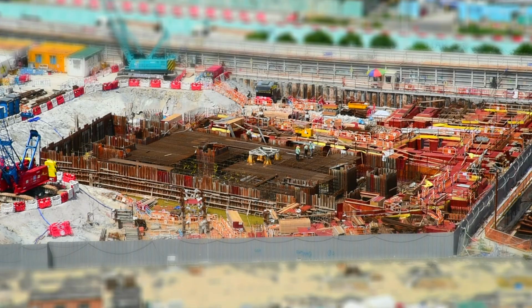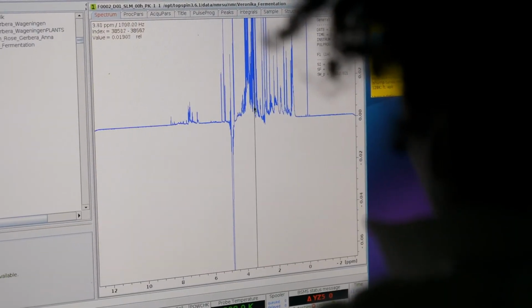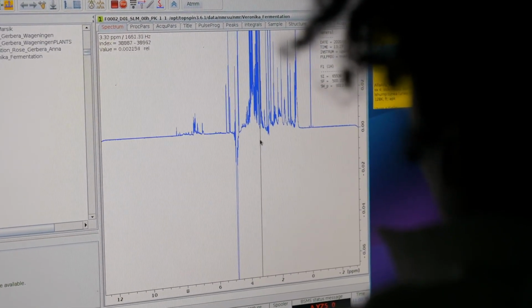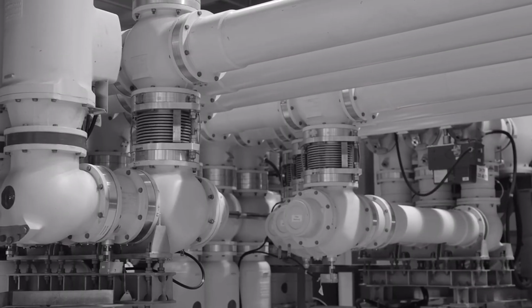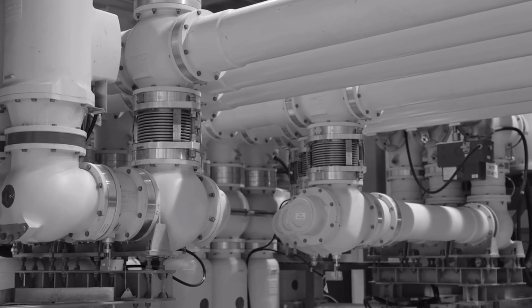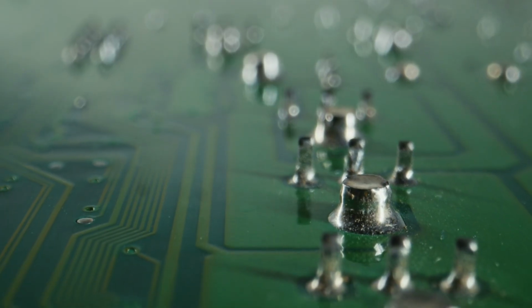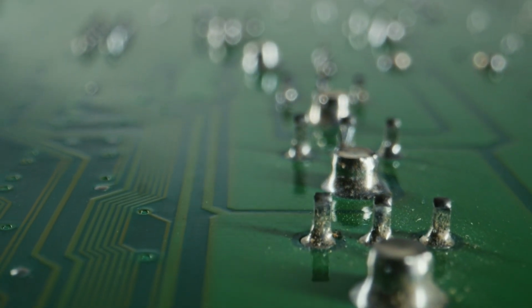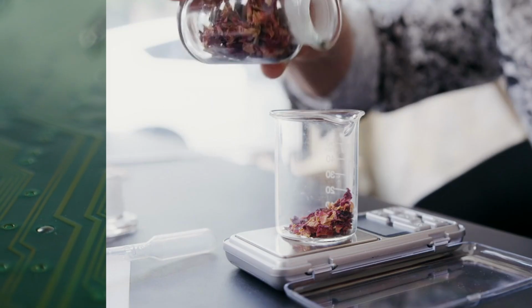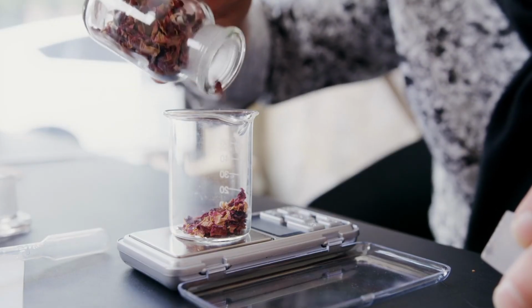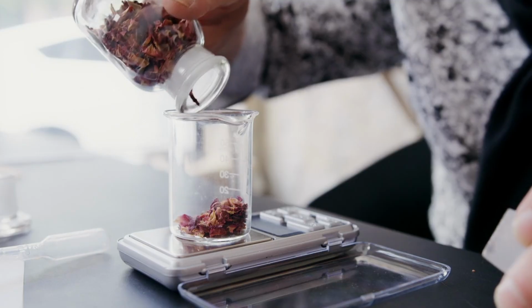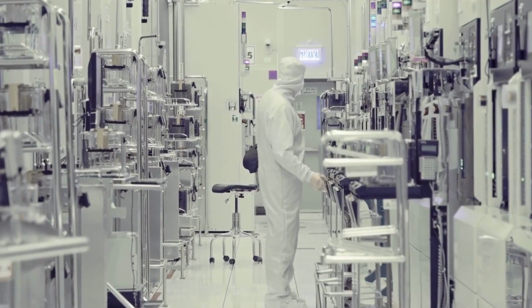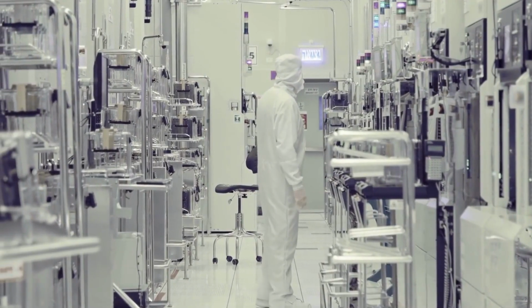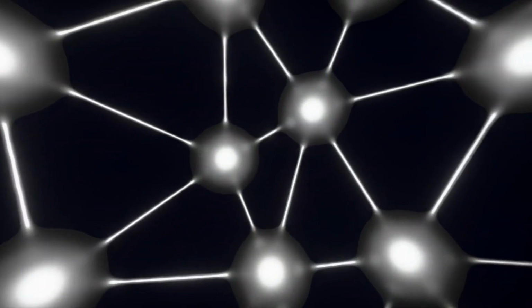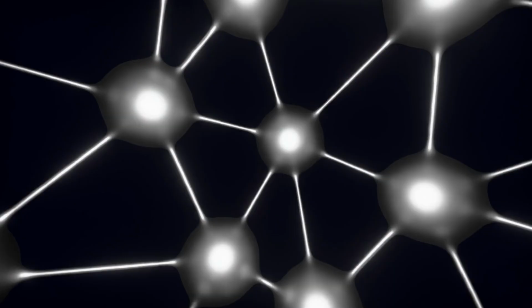Here is my honest read on what that means. The triumphalist version of this story says, China has effectively localized its deposition supply chain and is closing in on full independence. That is wrong. The process recipe gap at sub-7 nanometers is real and not closed. The 6N refining gap at leading-edge confirmed volume is real and not closed. Applied Materials leadership at the frontier is intact.